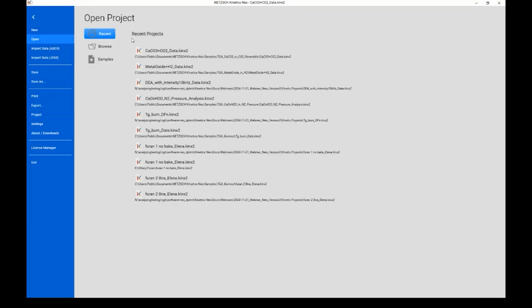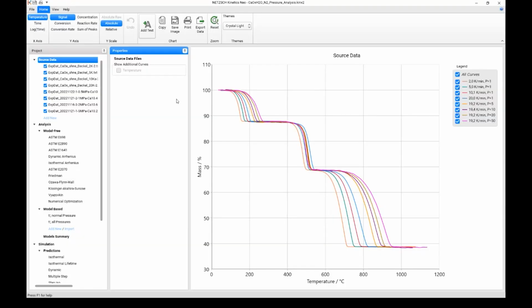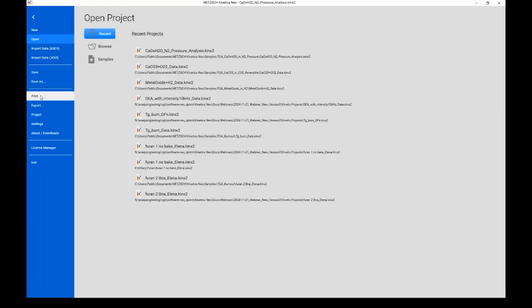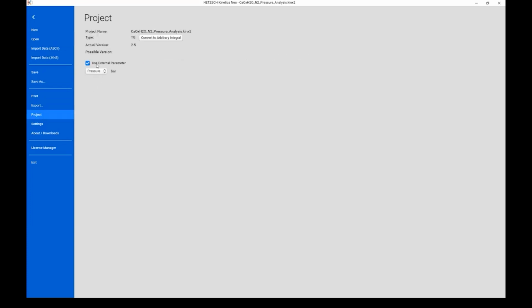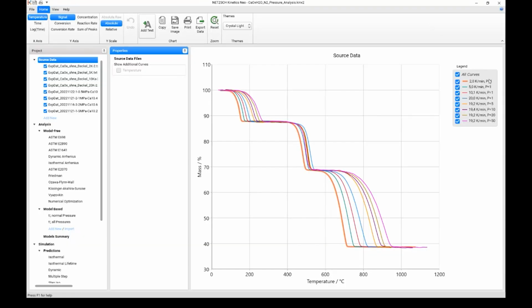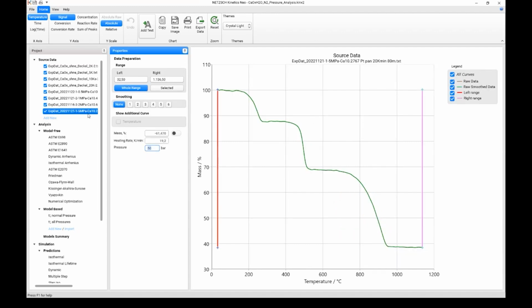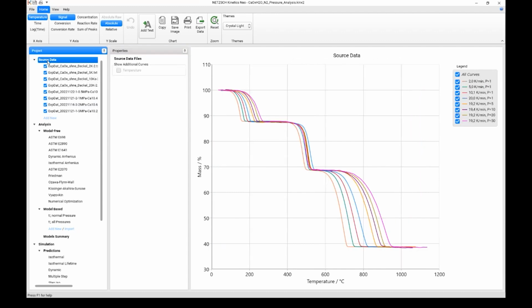Let's go to our Kinetics Neo software. Here I will open the calcium oxalate monohydrate. We have all the data for all pressures. In this case, we already have the project with the external parameter. In the legend, we see not only the heating rate, but additionally the pressure. For example, the first line has a pressure equal to 1, and the last one has a pressure equal to 50 atmosphere. Here, for the last one, it is 50 bar. Here we have 20 bar and all the others.